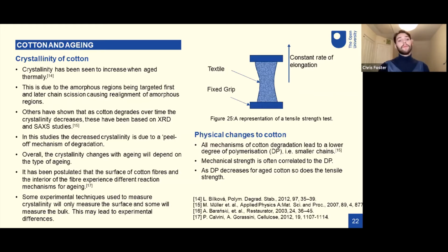Other studies have shown that with cotton degradation, crystallinity actually decreases. These have been based on X-ray studies, and these studies suggested the decreased crystallinity was due to a peeling off mechanism. So if we have the polymer chain, the subunit at the very end of the chain peels off and then it's followed along. And this was put down to occur in the crystalline regions. How the overall crystallinity changes with aging, in my opinion, from what I've seen, will depend on many different properties, depending on the type of aging and also the experimental technique used to study the crystallinity.